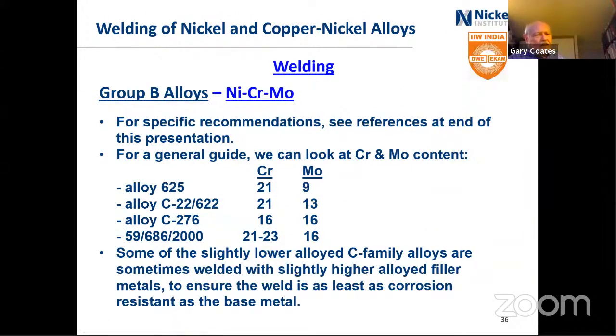If we move into the ones that are more commonly used in the chemical industry, the C-type alloys, here I'm showing the chrome and molybdenum, the major alloying contents other than nickel rather here. And the 625 had 9% molybdenum in it. That has a fair amount of corrosion resistance. The C alloys typically either have higher chromium or molybdenum. So the C22, 622 alloy has 4% more molybdenum than 625, so far more corrosion resistance.